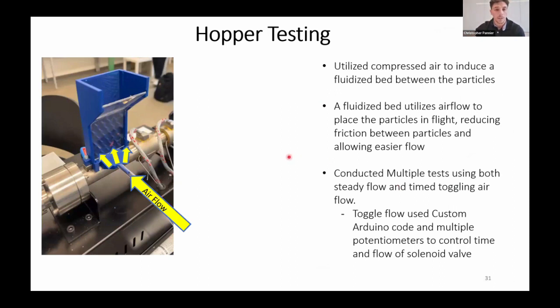As far as hopper testing, we filled the hopper with pellets and with flakes, and then took compressed air from the wall and blew it into the hopper. This in turn created a fluidized bed, which then allowed the particles to flow. We used a solenoid valve that turned on and off. As the hoppers are being blown and creating a fluidized bed, once the solenoid valve closes, the material was able to settle towards the bottom.